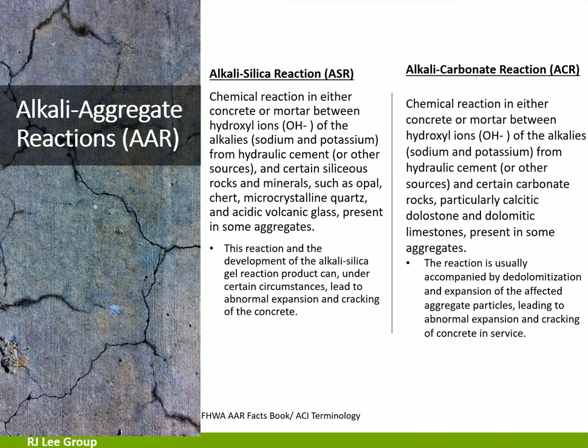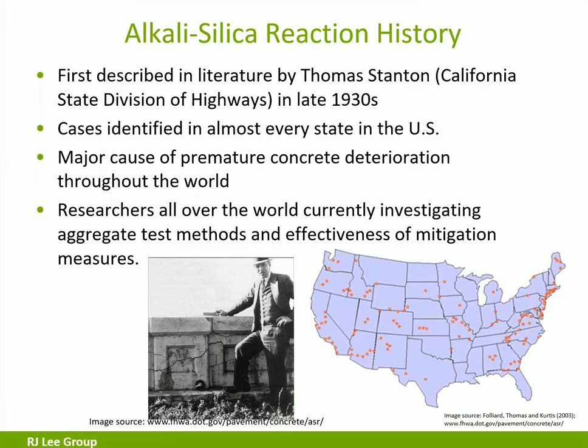So what is alkali aggregate reactivity? Well, we have two kinds. There's ASR, the chemical reaction of the hydroxyl ions of the alkalis with certain silica components of the aggregate. This reaction forms a gel, and under some circumstances that gel can cause expansion and cracking. The other type we have is alkali carbonate reaction, and that is going to be between certain dolomitic aggregate and alkali ions. We'll talk more about that in a minute.